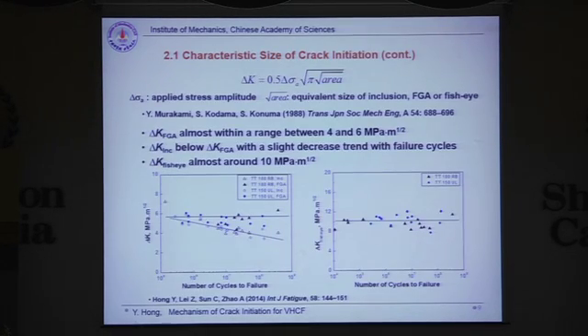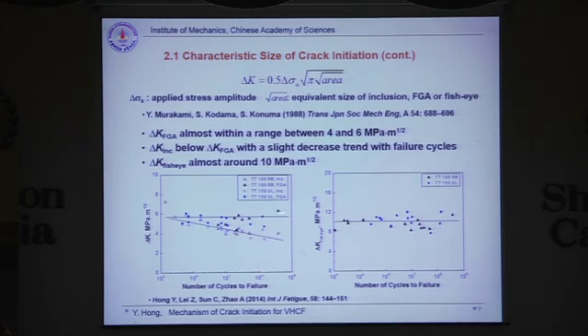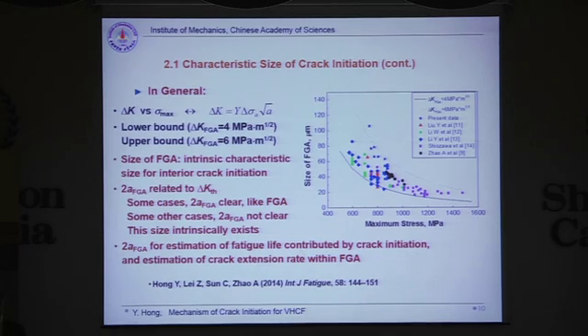We also calculate the delta K for the crack initiation region, that's delta K FGA, and the results show that this value is quite stable, in a range of 4 to 6 MPa square root meter. Then we collect a large number of data from our results and also from the literature, and we put two curves: an upper bound of 6 MPa square root meter and a lower bound of 4 MPa square root meter. We may see that almost all the data are within this range, not just our results but also the results from the literature, meaning that this value is quite stable.